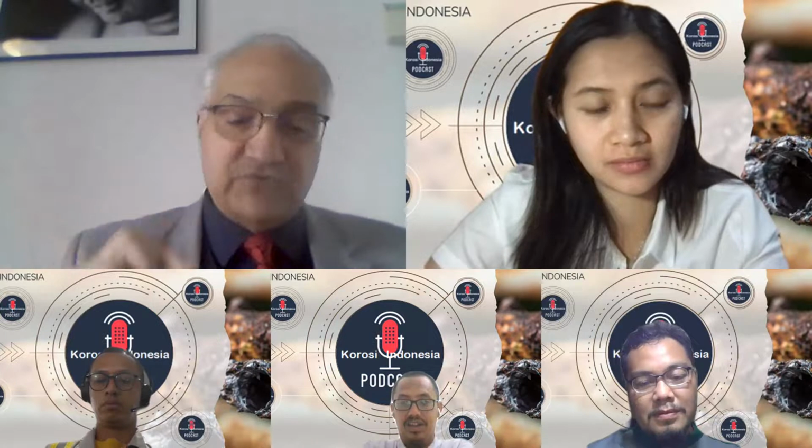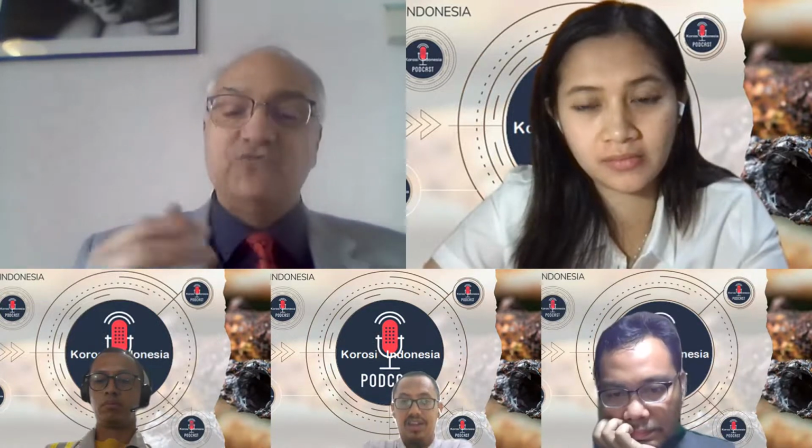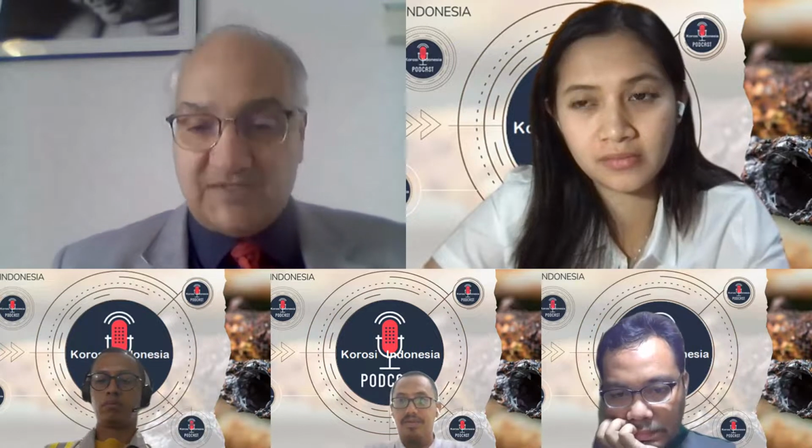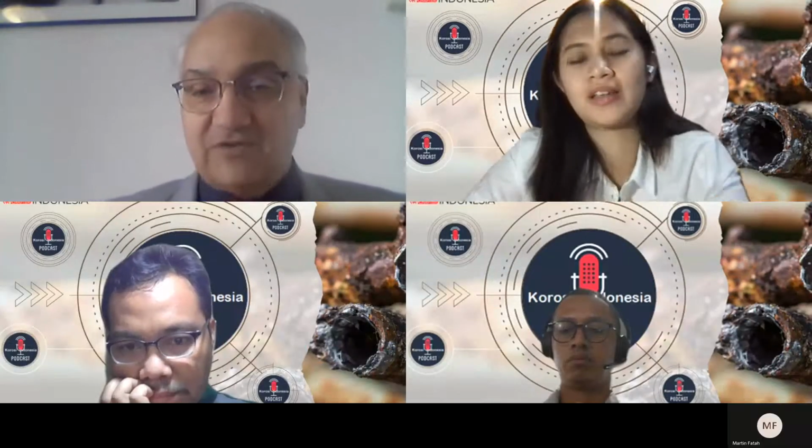They were saying that it is iron sulfide and it is SRB. I took the sample and applied a few drops of hydrochloric acid on it. If it was iron sulfide, you would have smelled H2S. Nothing. Nothing. It was not iron sulfide.